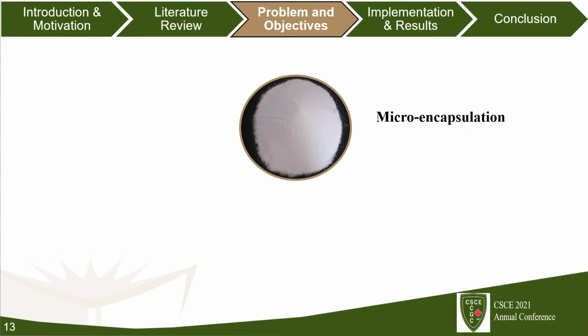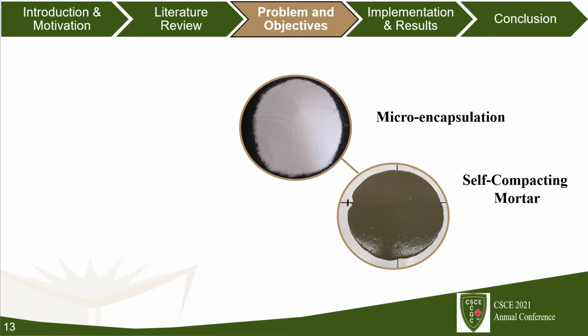In our research, we use microencapsulated material with a very small particle size, 3 micron. We used it in the self-compacted mortar as a replacement of sand with percentages of 3, 6, and up to 12%.